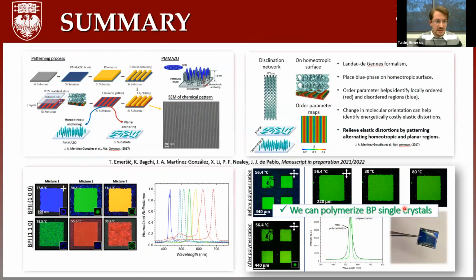So to summarize everything, we have a unique approach to form single crystals and monocrystals with these chemical patterns. They are generally applicable to different blue phases. We have numerical simulations that support us, that help us understand what's going on, so that we can get some parameters from the numerical simulations, right? And those parameters we use in the experiments. We have shown that these chemical patterns are generally applicable to different mixtures, and we can also freeze the system. So we have a 2-in-1 actually.